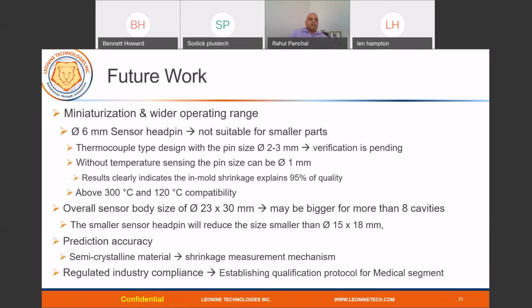So we are still working on another design which replaces the infrared temperature measurement with a thermocouple or a different type of temperature sensing, which is still more accurate than the infrared, similar to fiber optics or the thermocouple. That can reduce the pin size to almost 2 millimeter to 3 millimeter.